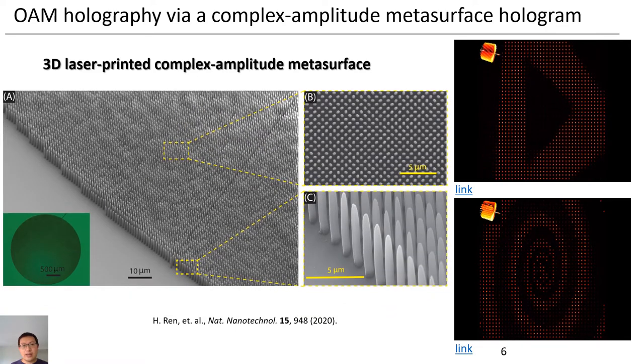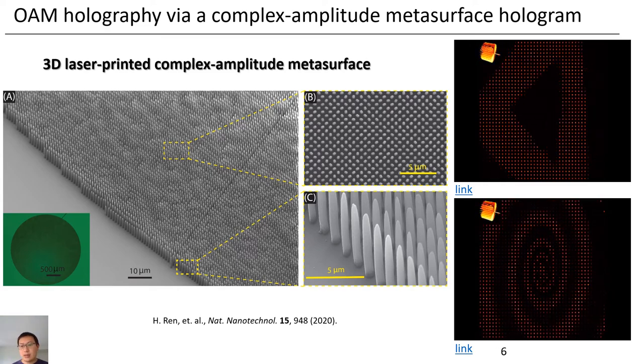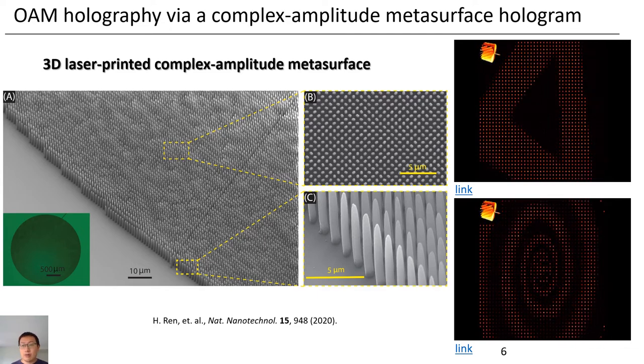As an example, this was fabricated using 3D laser printing technology. We fabricated the metasurface hologram to have a size of 2.5 millimeters by 2.5 millimeters. If we zoom in on this small area, we can see that the meta-atoms have different in-plane orientations to control their phase. In the oblique view, you can see that each of these meta-atoms is a high aspect ratio nanopillar with a different height. Altogether, we use this metasurface to experimentally reconstruct holographic video displays, where we can reconstruct two videos from two different image planes.